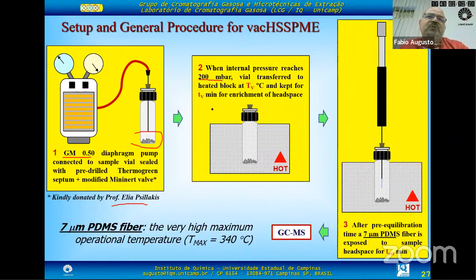The pressure goes to 200 millibars. It's not a very intensive vacuum. Then we transfer the vial to a heated block at a determined temperature and keep it some minutes there for equilibration. Then we expose the fiber, coated with 7 micrometer PDMS, polydimethylsiloxane, to the headspace, wait for some minutes, and then we pick up the sample and analyze by GC-MS. We use this fiber, which is not very used because it's too thin, because it stands very high temperatures, and in this case we need to use very high temperatures.